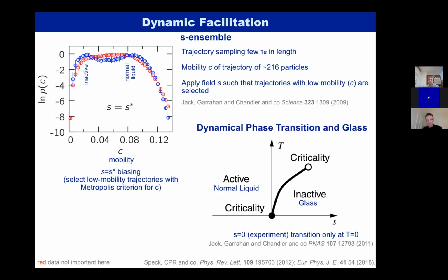Nevertheless, if we apply this biasing field S, then we can create a phase diagram of the system. What you see is that on the left-hand side is the active, normal liquid, and the inactive phase is on the right-hand side at higher S. And there's a phase coexistence line between the two. It's got a critical point at high temperature and also at zero temperature. But importantly, in this dynamic facilitation picture, there is only a transition at S equals 0, and the line only approaches S equals 0 at zero temperature.